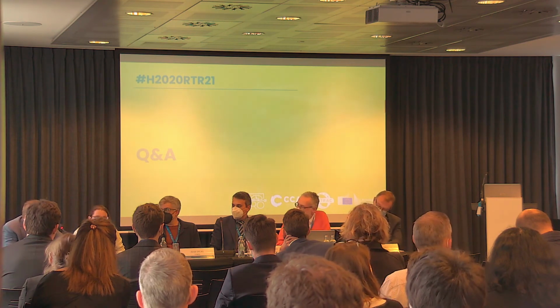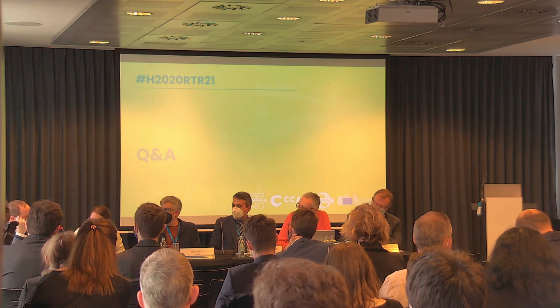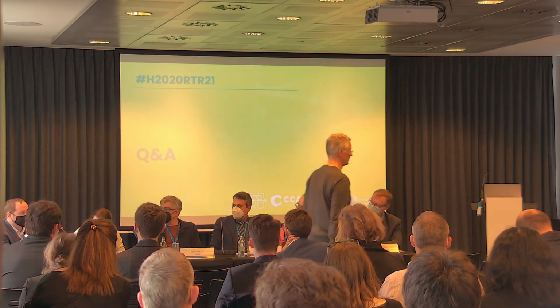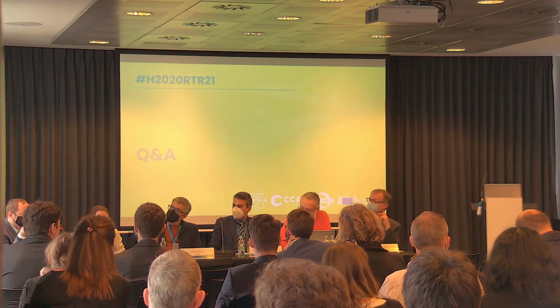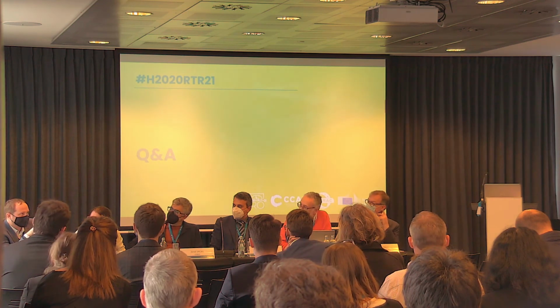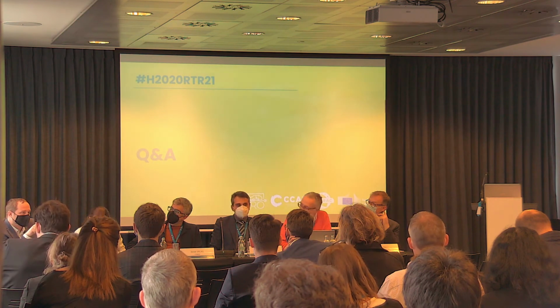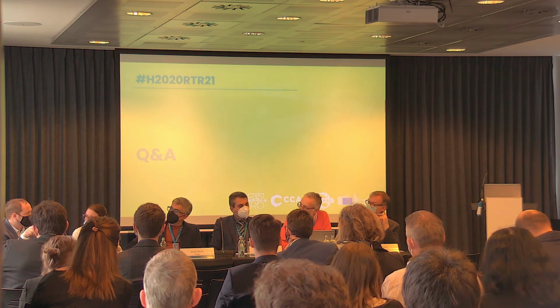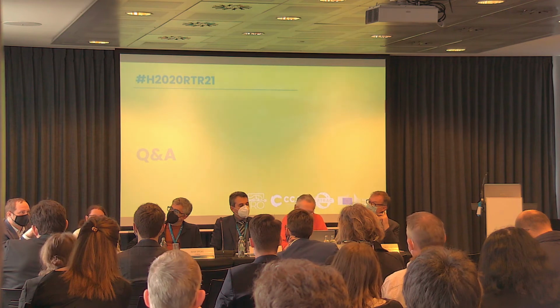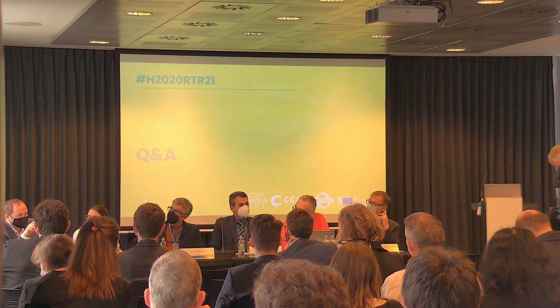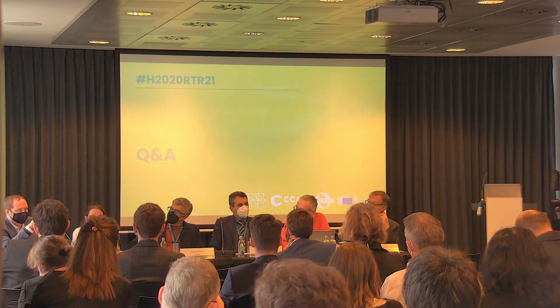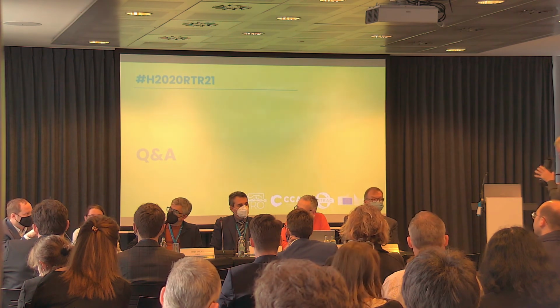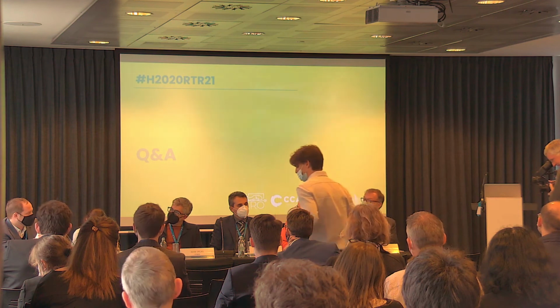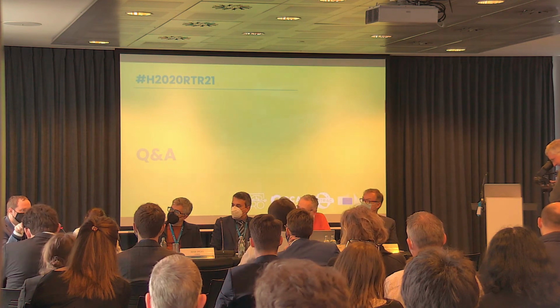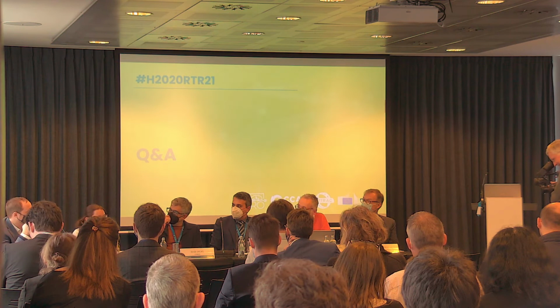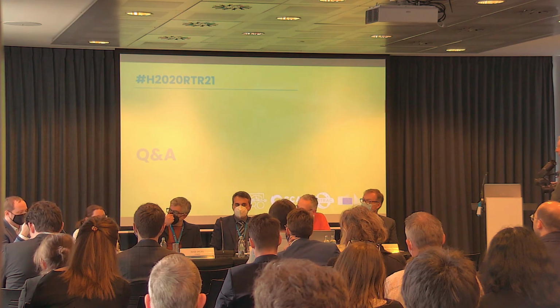We did it in Alizé. I believe it is reported. So it was deformation sensing. If you look at the discharge curve of lithium sulfur, it passes at least 3 times by the same voltage, no? So it's super difficult to do Coulomb counting, or to check it by impedance. Yeah, you have a peak of resistance at the first peak of discharge, no? But basically, what we did in Alizé is to monitor with the deformation. The deformation follows pretty well the state of charge and discharge, no? So, a deformation sensor for lithium sulfur.